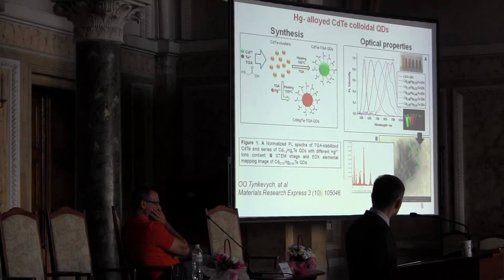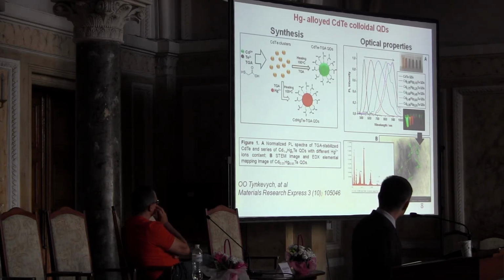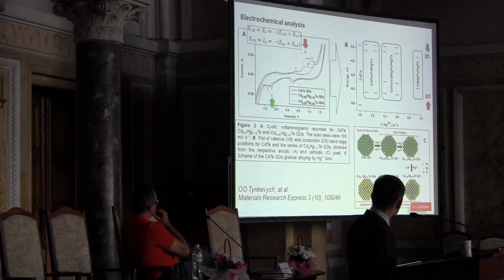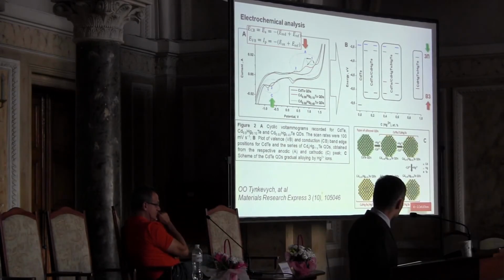And the idea here, and you can see it also for cyclic voltammetry measurements, is that you start with a cadmium telluride dot and you slowly form on the surface first the cadmium mercury telluride, and when the diffusion goes into the particle, you increase the concentration, you create basically quite a complex system, which could actually be mercury telluride itself at the surface, one of a few monolayers.